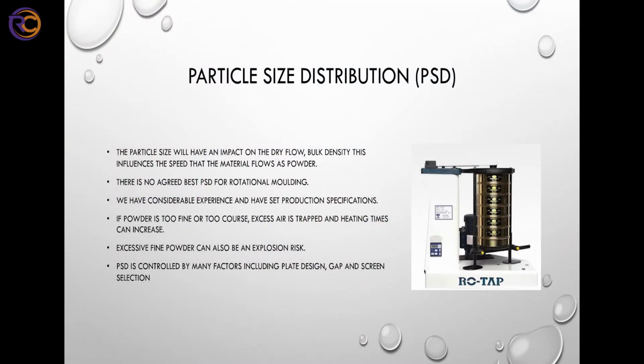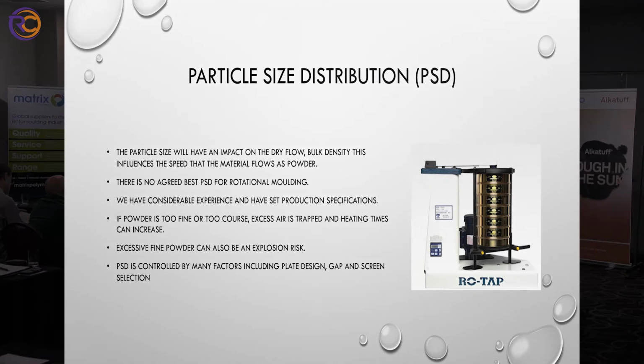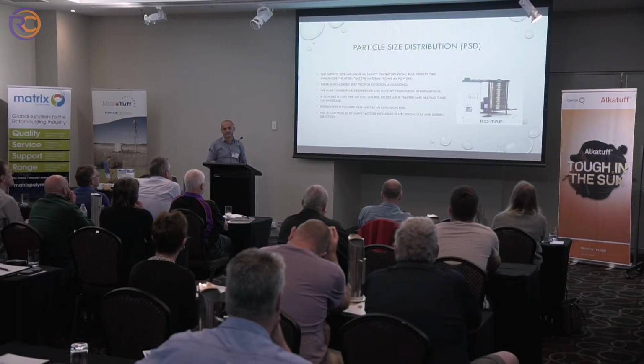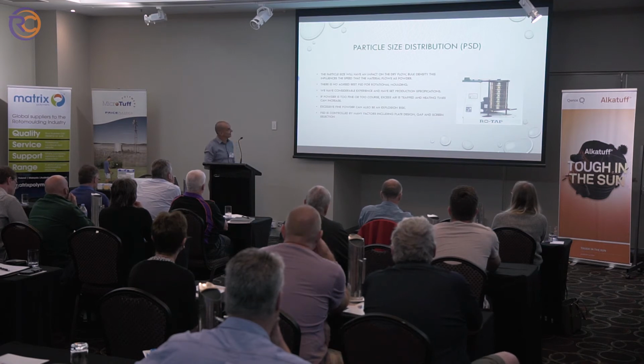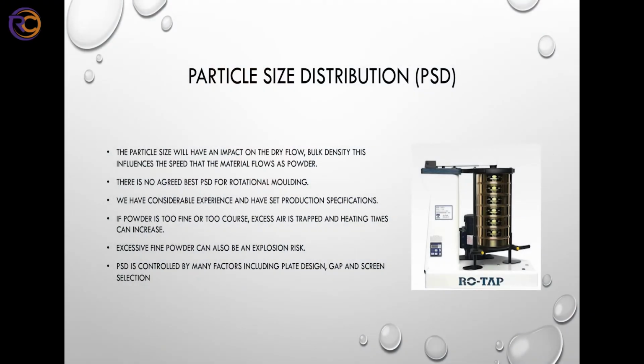So particle size distribution. The particle size will have an impact on dry flow and bulk density, but it doesn't influence the flow as much as the particle shape. There is no agreed particle size distribution for rotational moulding, but if you look at Roy Crawford's book, he talks about 500 micron grind. We have customers that we've done 400 micron grind, 500, even up to 1,000 micron, depending on what the end application is.